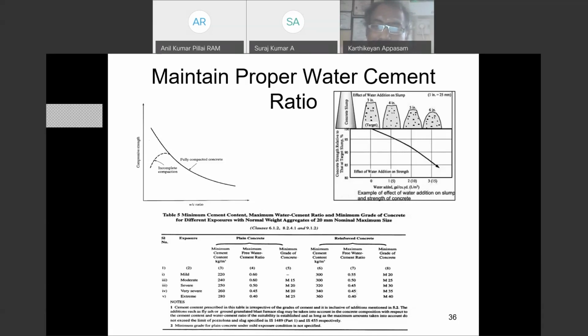Okay. IS Table 5 gives the minimum cement content and the workability for the slump. If the slump is shearing, don't use the concrete. You remix the concrete to adopt the proper slump. If the water cement ratio increases, definitely the strength reduces. Strength reduces. Okay.